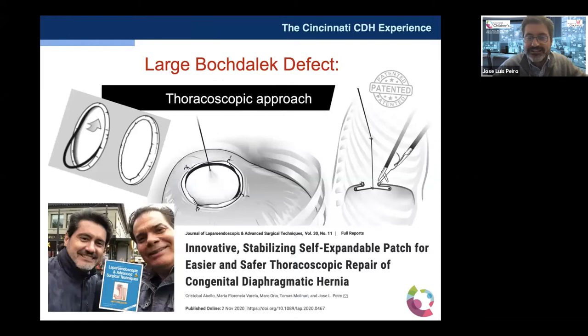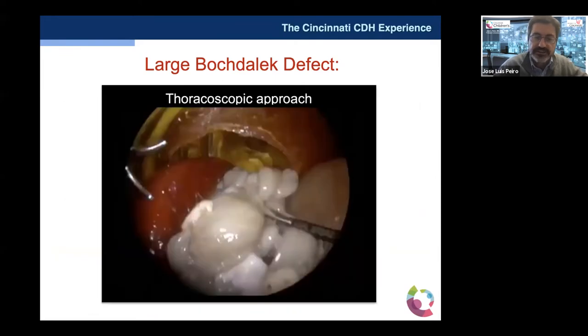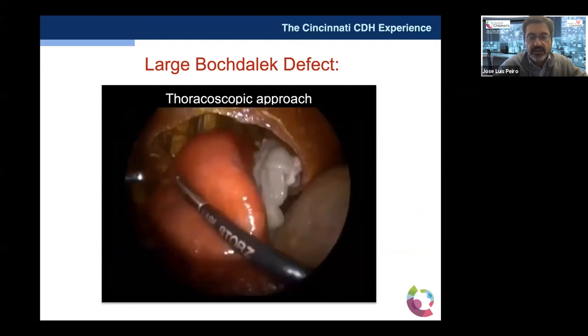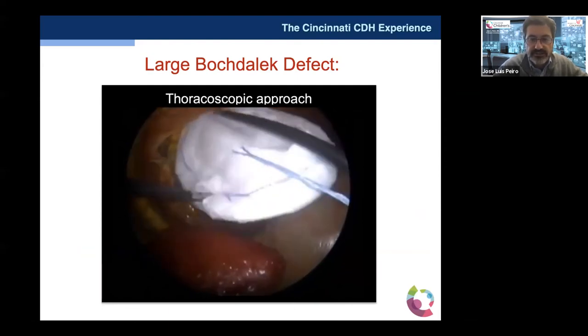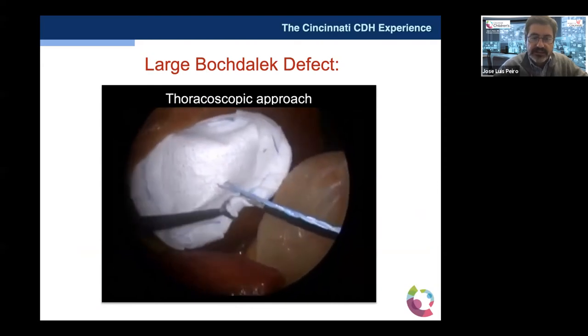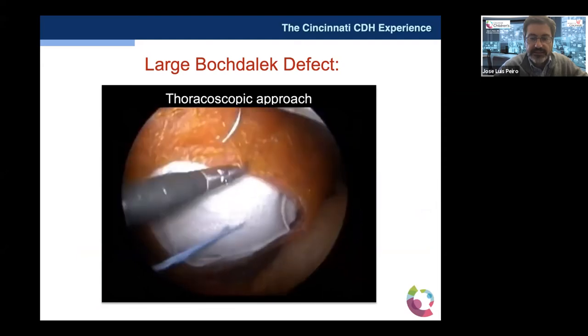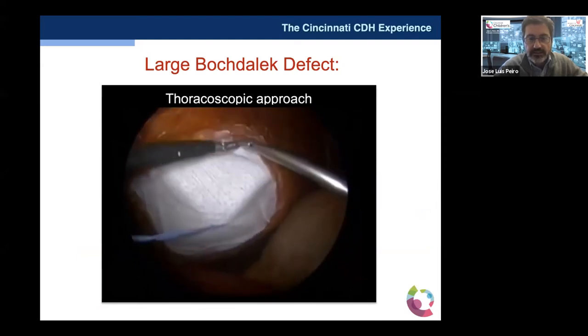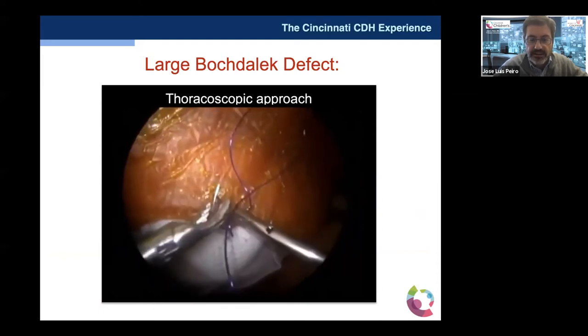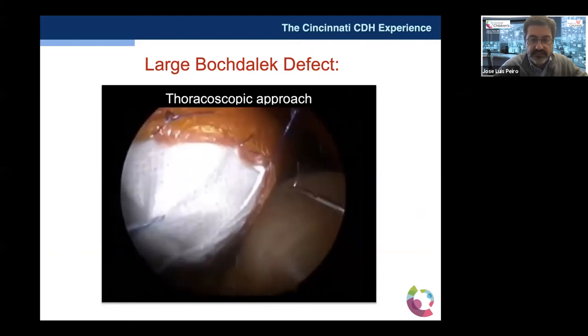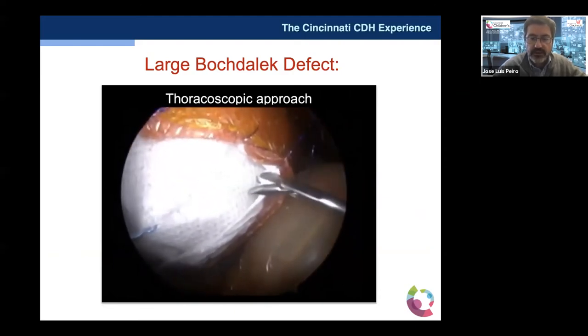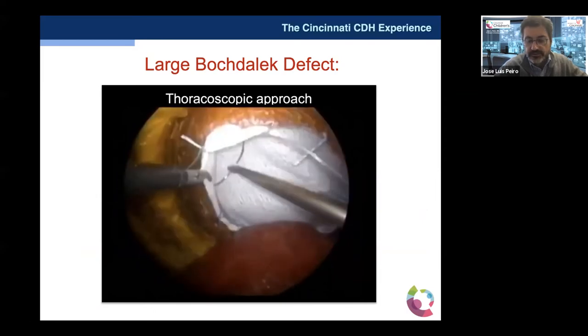And also, as Dr. Zani commented, we recently, with Dr. Abello in Colombia, designed a new patch system to be simpler for thoracoscopic application, using a folded periphery and also a stitch for stabilization. This is a simulation, so we can push all the viscera back to the abdomen, then we can pass this patch, and once it's in the belly, we can pull, and it is retained by the elastic ring. So we can actually do the suture from the muscle or the ribs to these folds in the patch, which makes it safer to avoid any injury to the bowel and complete the closure.